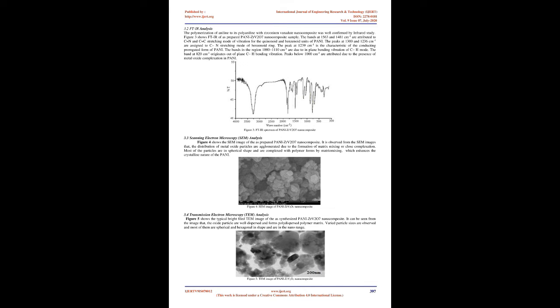Preparation of pellets. The powder of polyaniline/ZrV2O7 nanocomposite so obtained is crushed and ground finely in the presence of acetone medium in an agate mortar. This powder is pressed to form pellets of 10 mm diameter and thickness which varies from 1 to 2 mm by applying pressure of 90 MPa in a hydraulic press.